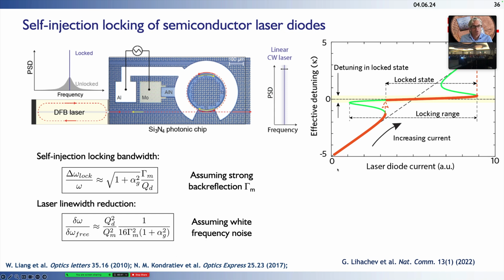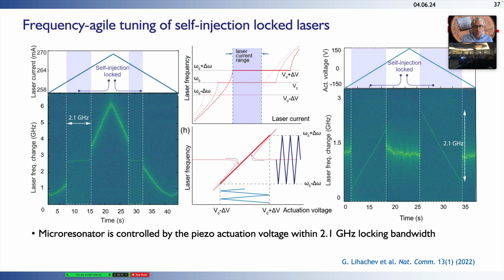Now, when you start to tune the laser current, you will see a range in which the laser frequency hardly changes because it is locked and pinned to the microresonator, the so-called self-injection locking range. Here, this provides one opportunity. If you now start to tune the resonator with an aluminum nitride actuator, you can create a frequency agile laser because in this case, the DFB will follow the external modulation. This can generate tuning with quite substantial actuation bandwidth, in this case 2.1 gigahertz.